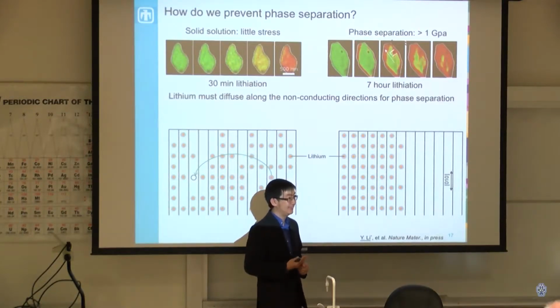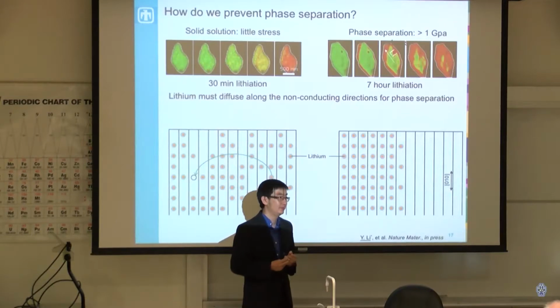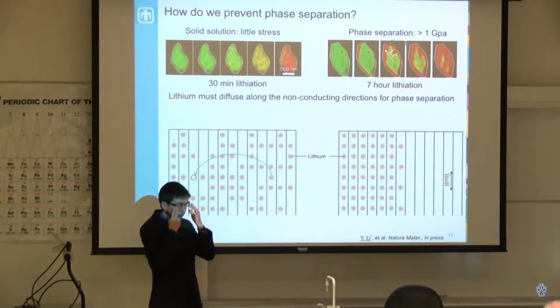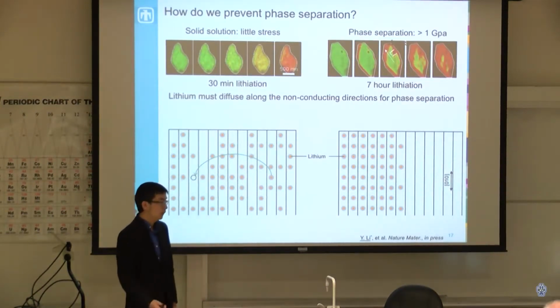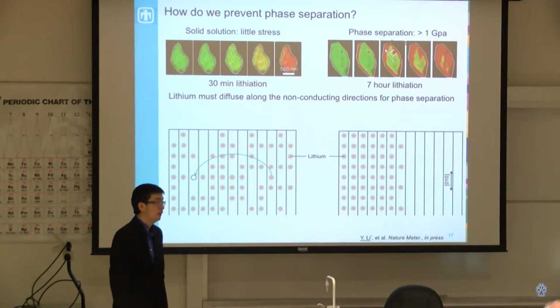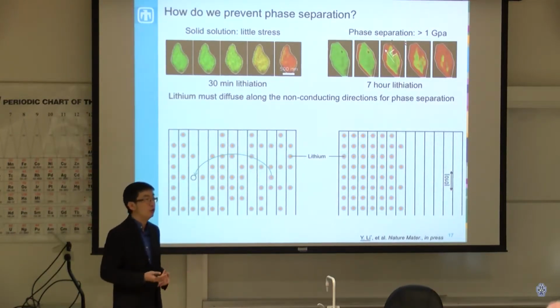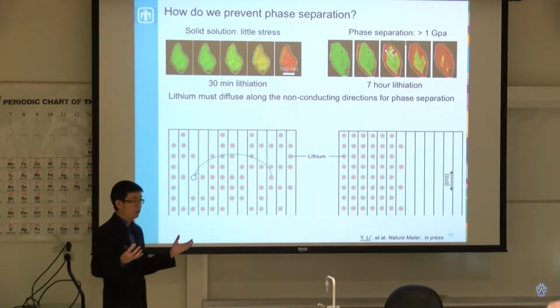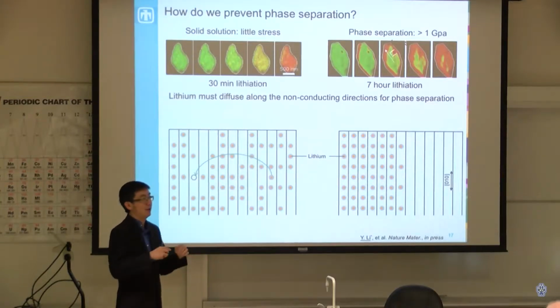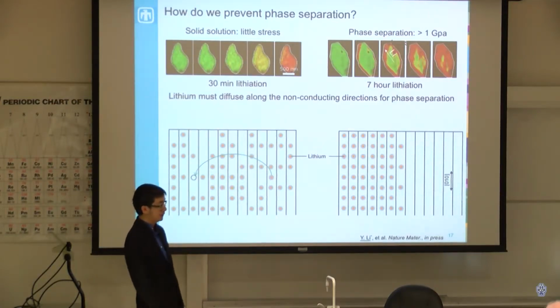Okay, so help me one more time. I got that now, but the mechanical stress, what's the negative downside of that in terms of the efficiencies? Is it actually breaking up these materials? Or is it that it's not efficient because there aren't as many channels for it to be happening? Generally, it's one of the mechanisms by which the battery could delaminate, or potentially lose capacity over time. It might not be the dominant mechanism, but it's one of the ways a battery can start to fail or degrade over time. Imagine you have one crystal that you engineered really well, and then all of a sudden it breaks in half. It's possible that the other half will not be connected, so it would be really hard to charge up the other half of the material. Thanks for the question.